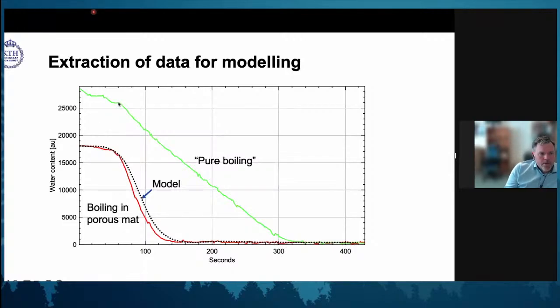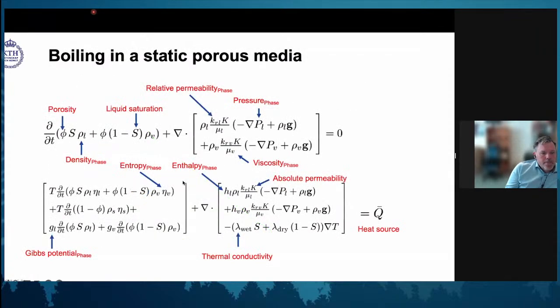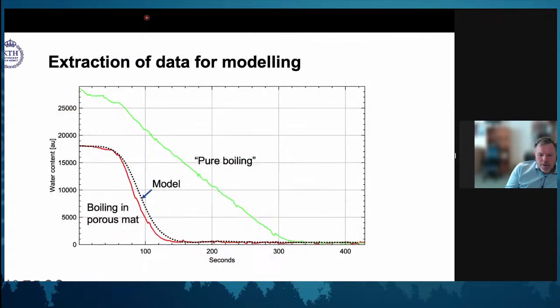Just as an example, the alternative is to just look at pure boiling, then it's just linear with time. So you supply heat, water evaporates. It's all about the time spent heated. But by doing this modeling, we can actually start to extract data and parameters. So some of the parameters here for the different phases can be extracted by fitting the model. And as doing this, we can actually see that next steps would be to develop this and include dynamic features. And you would like to go so far that you could develop a model that can be used for controlling the industrial process. All of this based on that neutrons will give you a possibility to measure something that is almost impossible with any type of other technique.